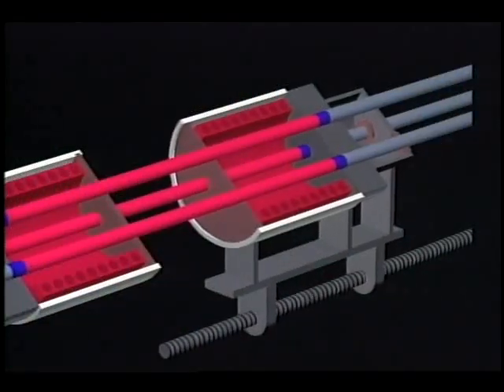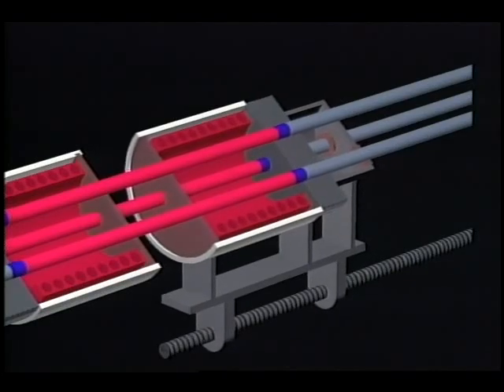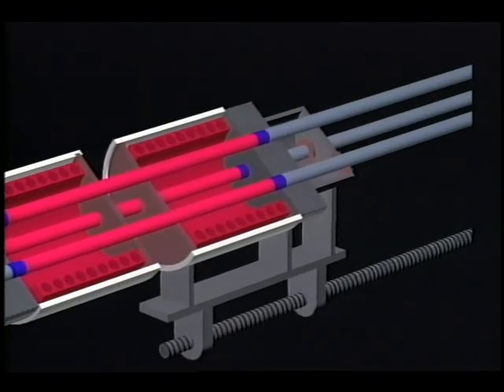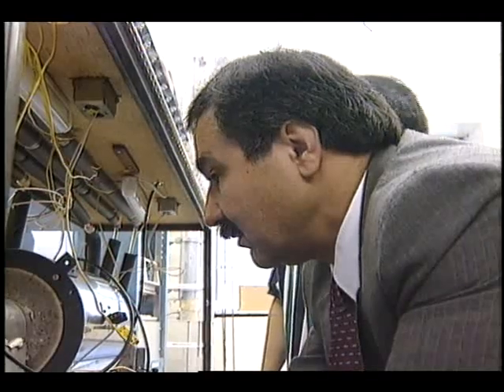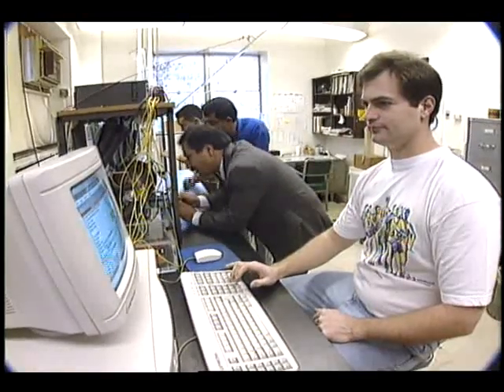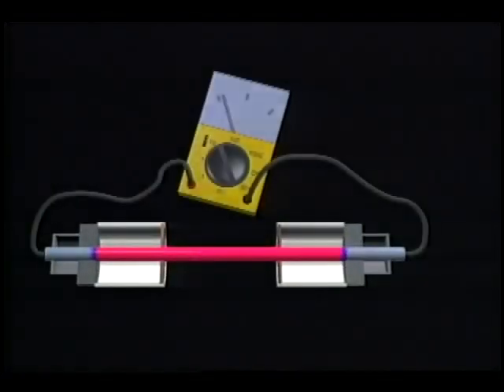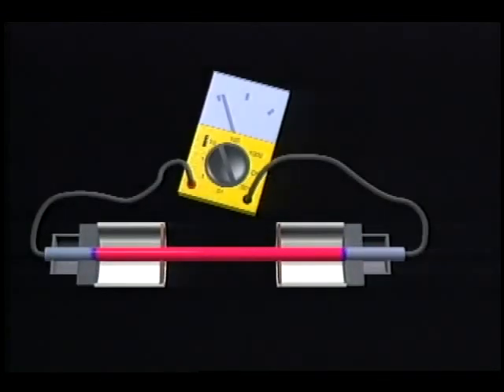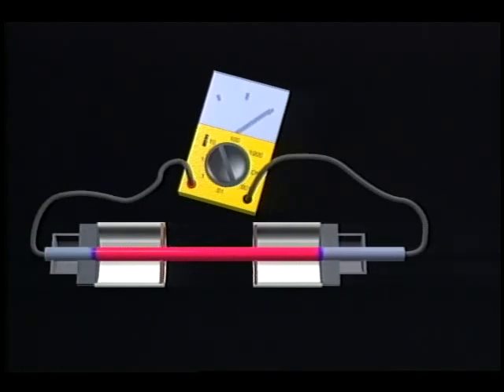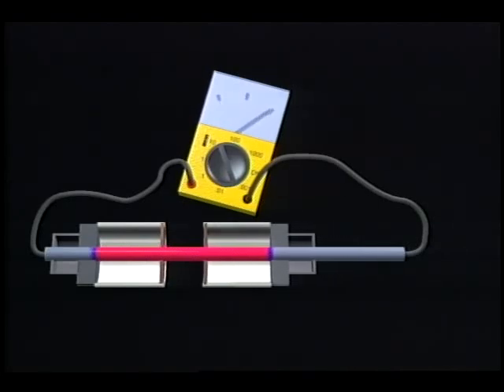Although MEPHISTO processes all three samples simultaneously, different measurements are taken of each sample. The Seebeck technique is a non-intrusive way of measuring the temperature of the solid-liquid interface. A voltage across the sample is created by a potential difference between the stationary solid and liquid interface and the moving solid and liquid interface. The level of supercooling at the interface in the moving furnace is determined from this voltage difference.